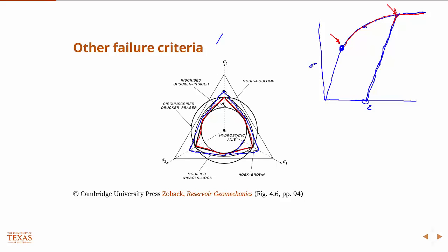You take this discrete step and load, the only thing you know how to do to evaluate the stress is to say it's elastic, and then you find yourself, because it's a discrete step, outside the yield surface. Okay, but this is in violation of that constraint. It's not allowed. You have to be inside the yield surface or on it. So basically what we do is we solve a constrained optimization problem to get us back on the yield surface, and we enforce that with something mathematically that's essentially a Lagrange multiplier. So we get ourselves back on the yield surface.